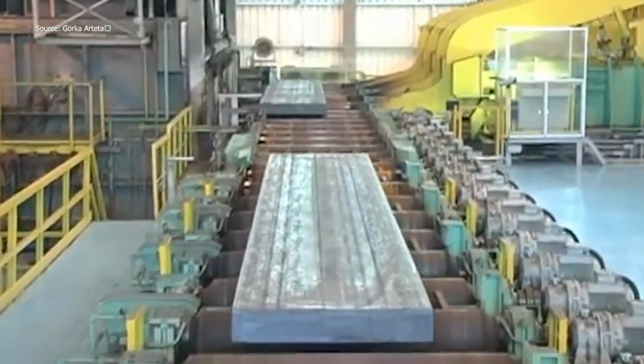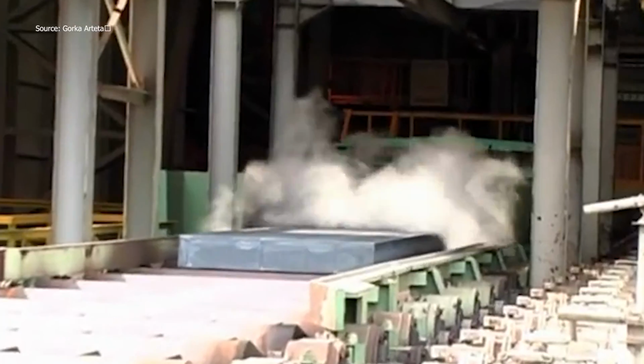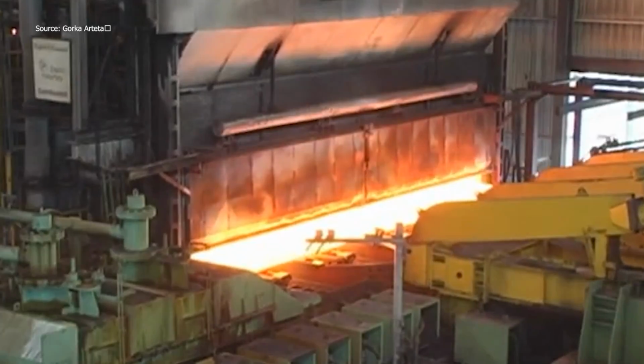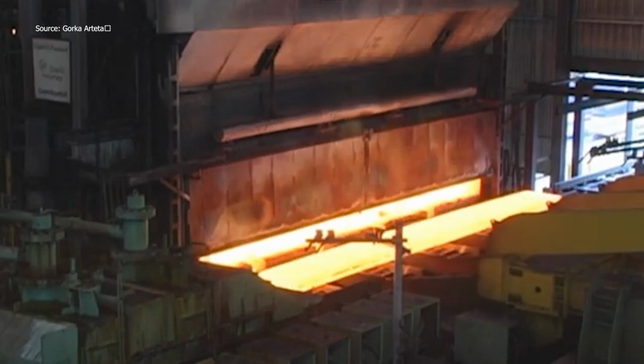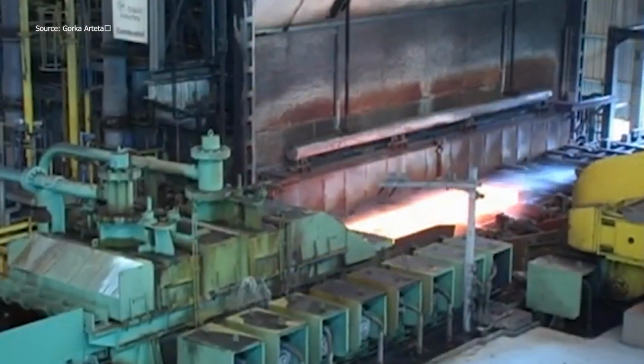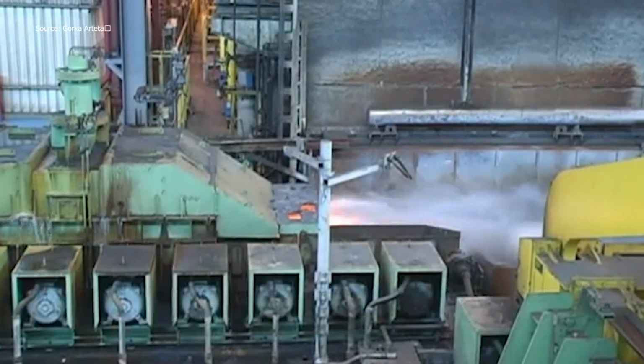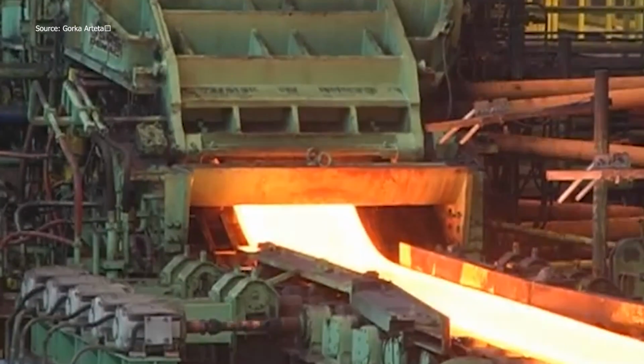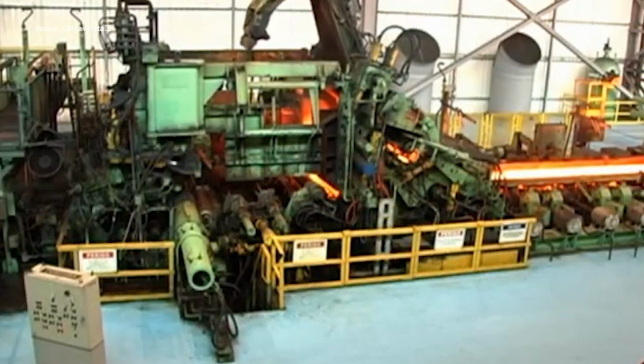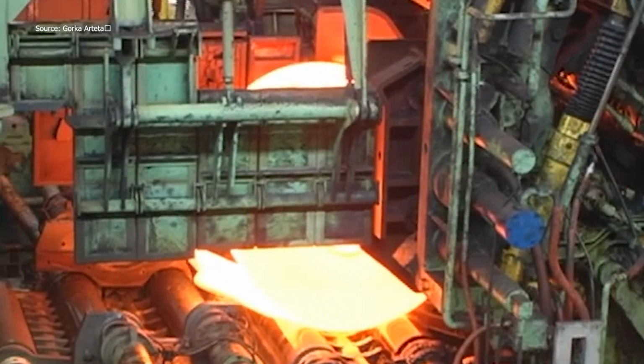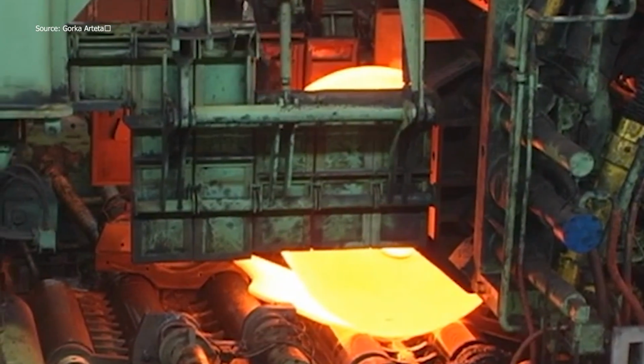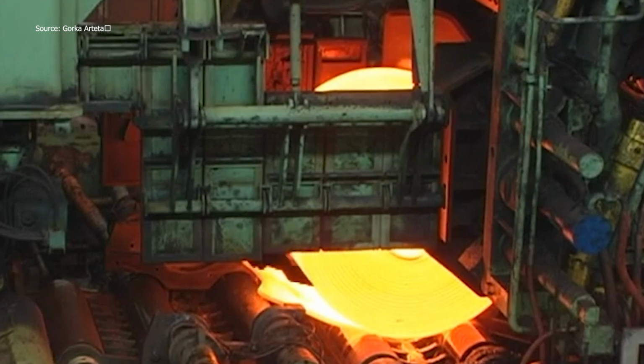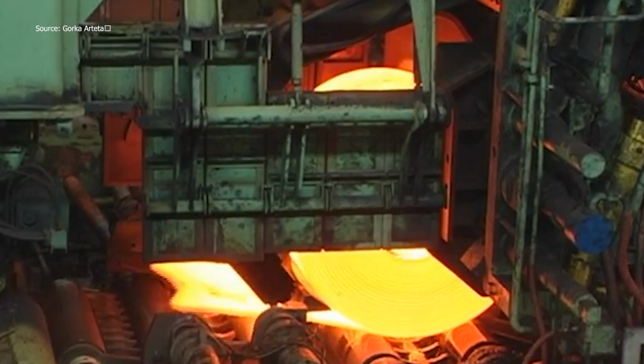Steel heats up and moves forward. At CST Laminacao, thick steel slabs start their journey as they are received, reheated, and transformed into thin coils. The process begins with unloading and sequencing slabs, transported by overhead cranes to the reheating furnace. The slabs reach around 1,200 degrees Celsius, the perfect temperature for rolling. Rolling mills then reduce slab thickness from 200 to 250 millimeters down to 20 to 40 millimeters over multiple passes. A vertical edging mill trims the width to precise dimensions. The slabs, now called blanks, are coiled and temperature homogenized in the coil box.